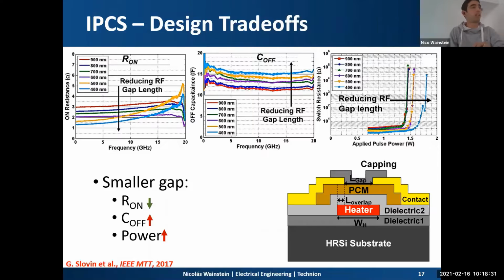Another design trade-off is the distance between the electrodes. A smaller gap between the two electrodes will reduce the on resistance, as you can see here, but will increase the off capacitance. Also, the smaller gap will increase the heat spreading through the RF contacts, and therefore will increase the switching power, as you can see here. The thickness of the PCM will also affect the RF performance, of course, because a thicker PCM layer will reduce the sheet resistance. On the other hand, we will need more power to switch the phase of these materials.